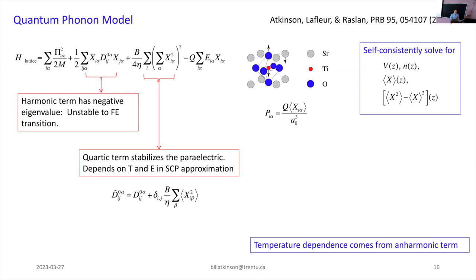Okay, and so the two things that make this a model for a quantum paraelectric, the first is that this matrix D for the spring constants has a negative eigenvalue, which makes it unstable to a ferroelectric transition. And the second thing is that this term is stabilized by the quartic term. The quartic terms are hard to deal with. And I always just go straight to mean field theory until somebody tells me I can't.